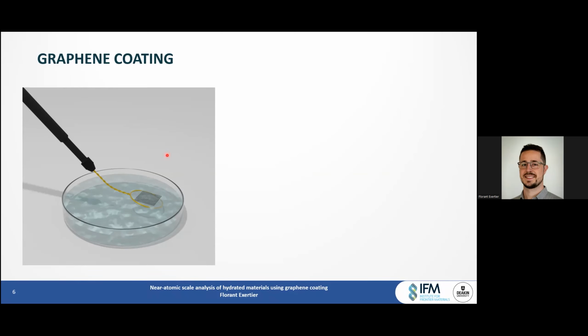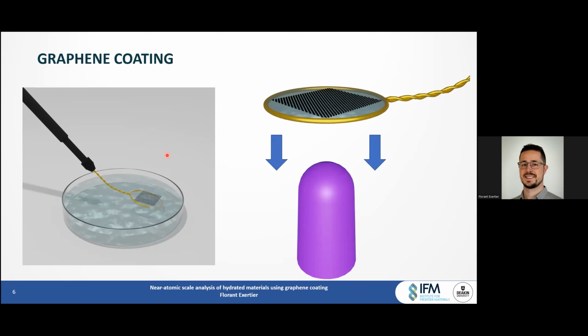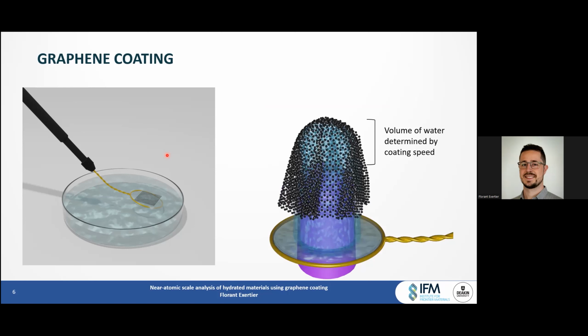Then the graphene foil is scooped using a wire loop and then applied to the tip of an atom probe specimen. In the case where liquid needs to be analyzed as well, we can add a little volume of liquid to the solution, and then the graphene foil with the liquid are dropped and applied on the tip of the specimen. And in the case of encapsulation of liquid, the volume is determined by the coating speed.